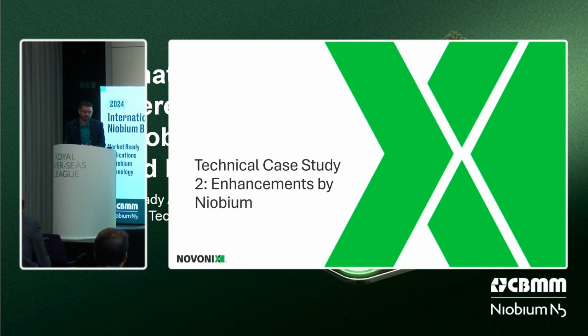So I want to briefly touch on, again, this is just scratching the surface on what niobium can do in an all-dry zero-waste process. We started a project a few months back with CBMM, exploring NMC synthesis for the high nickel case, 811, using our process while also using niobium in a few different ways. We have a lot of testing in progress, but what I have to show today is some of the results we've collected thus far on surface coating. We also have some tests in progress on using niobium as a dopant, but stay tuned for another version of this conference for those data.